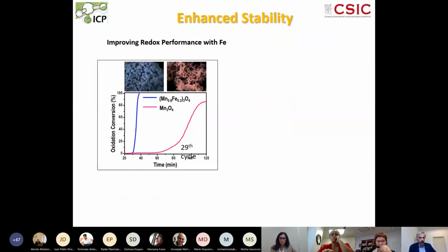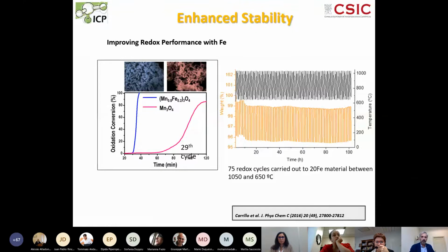Regarding the stability, that's a huge progress, because if you compare the material without any doping, you can see here that the reaction of oxygen recovery after 29 cycles is very slow. It's taking almost 2 hours, but in the case of the iron-doped material, you can see that it takes only a few minutes. So we have a great improvement. You can see here also what is happening when we run 75 redox cycles up and down. We are taking and releasing oxygen, everything together. You can see that this is fairly stable, although we have some drift in the baseline, but in the end, we have the same properties of the material, so we don't have any degradation.